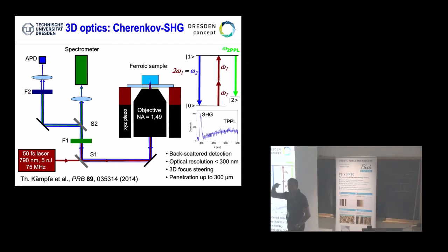That's exactly our excitation level. Then we have 2 processes as a decay level. One is photoluminescence, which gives a bright background, so you get shininess in the visible range, at different wavelengths. That is two-photon photoluminescence. And you get a direct transition, the second harmonic transition to the ground state.